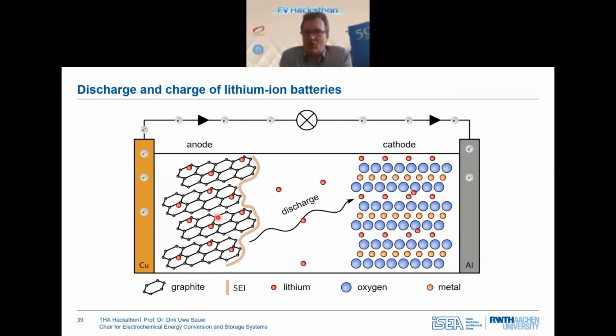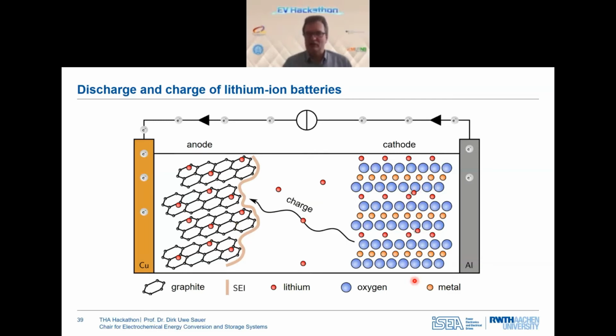And this is what is called an intercalation battery, because both electrodes are so-called intercalation electrodes. This means their crystal structure remains unchanged during the charging and discharging. The graphite structure remains, but also the metal oxide structure we have here remains, and just during discharging, the lithium ions are going out of the anode material and they diffuse into the cathode material. And during charging, things are just the other way around. During charging now, the electrons go the other way around, and the lithium ions go from cathode to anode.